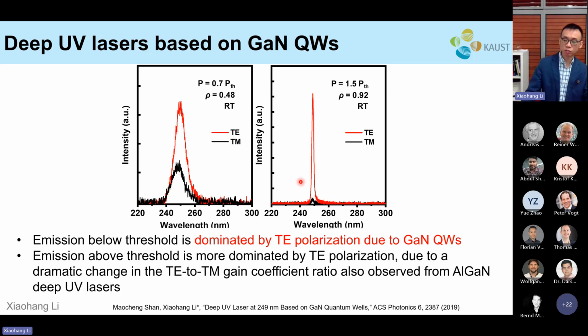For the above the threshold as well, we have a TE dominated spectrum, indicating that the use of gallium nitride indeed can leverage its TE dominant emission for lasers and LEDs.